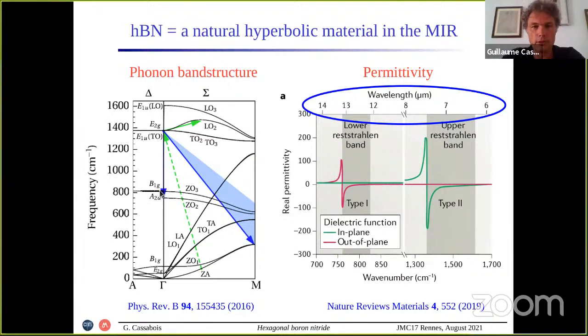For the lower Reststrahlen band, it is type 1: we have a resonance out of plane. And it is type 2 for the upper Reststrahlen band, where the electric field is absorbed in the plane. This gave rise to many applications I have no time to cover today, but this is really a first example of a good surprise, the fact that hBN, because of this anisotropic structure, is a naturally hyperbolic material.